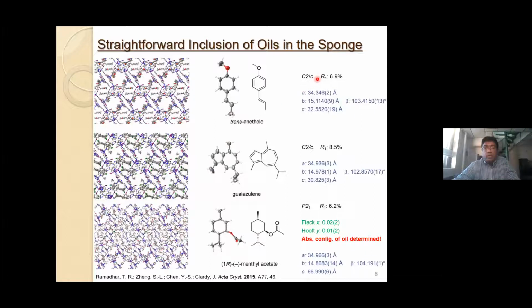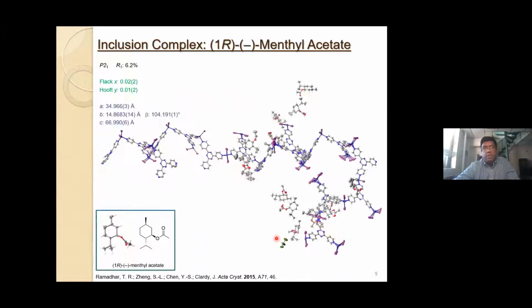Now, we were able to get good crystallographic data. This is the main statistic that you want to look at. This is the R1, the basic agreement between the experimental electron density map and the calculated electron density map. And there's good agreement. You basically want these to be under 10%, and they are. The most interesting case here, though, is 1R-methyl acetate, which is a chiral oil. And through this technique, I was able to determine the absolute configuration of this oil through X-ray crystallography unambiguously. So it really demonstrates the power of the method.